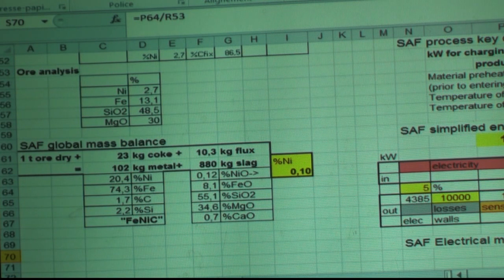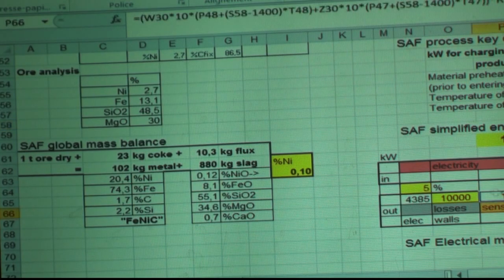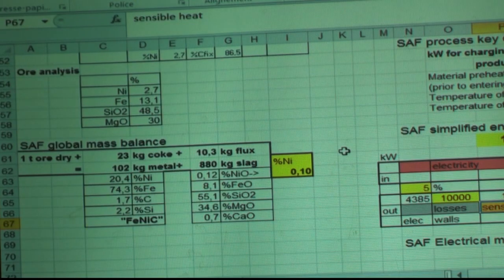I explained to you that between the slag and the metal there is 50 to 100 degree difference. But normally I put here the temperature of the slag, because metal is less important. As I told you, in this formula it's easy to change to say that metal is 100 degrees less. We could make minus 100. You understand? This can be done easily. But the important fact is that they tap the slag at 1600 degrees and not 1400 degrees.